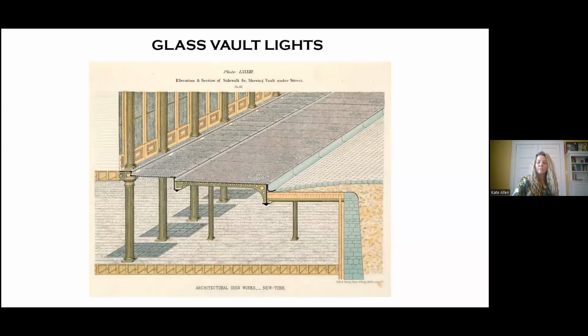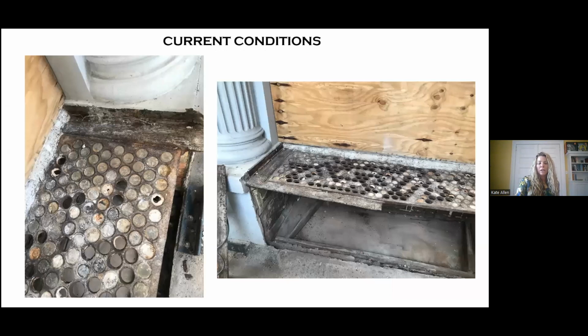Okay, so in the 1850s, glass vault lights began to appear in the city as they permitted daylight to reach the dark basements beneath the sidewalk. And so this created more rentable and usable space for building owners, and also gave the storefront more character and street appeal. For the most part, these panels are really in a state of disrepair. We see these all the time. We see failing glass. We see structural failure, not only of the panels, but of the framework. And salt and water have really deteriorated both the sealant and the coating systems, as you can see.